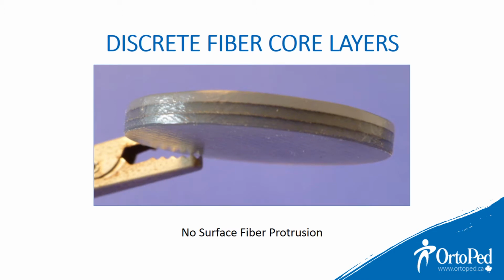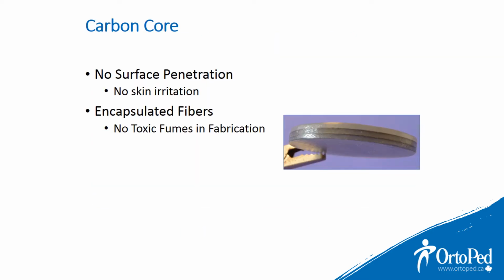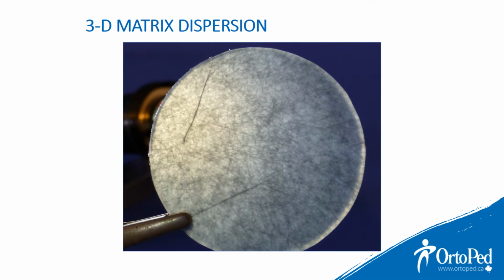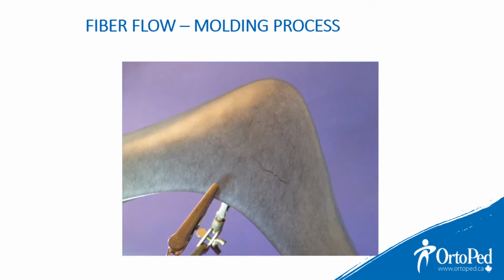There is a total of 5 layers, 3 polypropylene, 2 carbon, with no exposure of the carbon. No surface penetration, so there's no skin irritation, which you usually would find with carbon. Encapsulated fibers, no toxic fumes during the fabrication process. Carbon is dispersed in a 3D matrix. The carbon fiber flows throughout the molding process, as shown here.